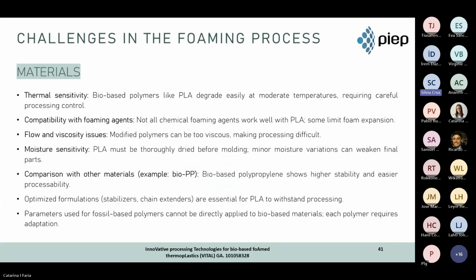So during the project, when bio-based thermoplastics were processed using foam injection molding, several specific challenges arose due to the material properties that affect part quality and consistency. To start, we have the narrow processing windows, which present lower thermal stability, tight margins between melting and degradation, and greater shear sensitivity of viscosity, resulting in a higher risk of degradation, discoloration, or gas cell collapse if conditions are not precisely controlled.